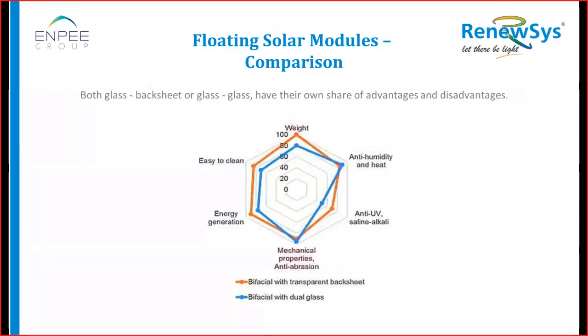floating solar. And the key worry point where everyone thinks about floating is the humidity and moisture, and that will be a dangerous part. But generally, in the coming slide when Rahul will explain, it is very simple: the humidity of water bodies is definitely 10 to 15% more than normal areas, but the temperature is lower. If temperature is less, then definitely the polymers used in the modules are not going to expand much in the molecules, and the pores will not be very expanded to allow moisture to go inside. So there is a trade-off between temperature and RH for the moisture to ingress inside the module.